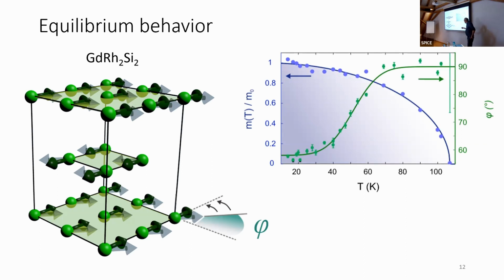So what is this angle? This angle shows us that the spin structure, the entire spin structure, not one individual spin, but all of the spins, I'm going to have to wave my hands now. All of the spins rotate coherently as you heat up the system by about 35 degrees. This is a relatively large effect.